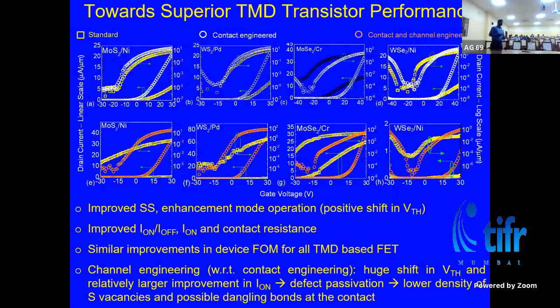Now, this is graphene. Let me move quickly to TMDs. In TMDs, as I've shown, we introduced those contacts. Now, as a function of those contacts, there are two things that we did. We introduced those sulfur interstitials in the contact region, and we also tried to use that sulfur for passivating the channel. That was separate, which I have not covered here in the interest of time.